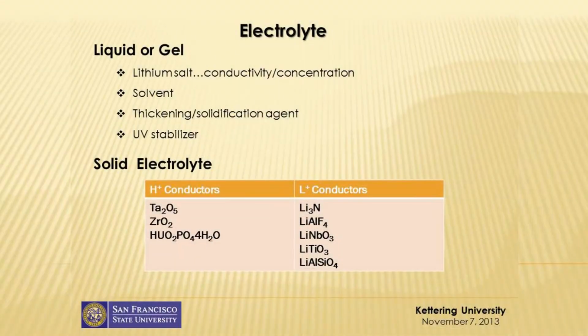There are solid electrolytes, mostly made by physical evaporation or wet chemical deposition techniques. These are the examples. The most used proton conductors are tantalum pentoxide and zirconium oxide, and for the lithium ones, lithium nitride, lithium aluminum fluoride, lithium niobate, lithium titanate are the most used examples for these electrolytes.